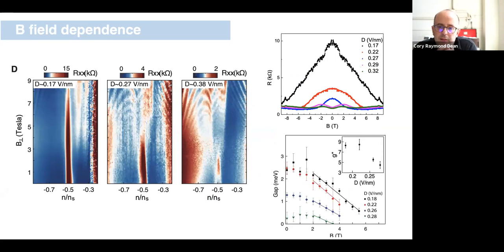Okay, so one of the questions immediately is, what's the magnetic order of this ground state at half filling? And the answer I'm going to give is that for this system, at least so far, we don't have a good understanding of that. I'm showing here some magnetic field dependent measurements of the half band insulator gap, so how that gap evolves as a function of B and as a function of displacement field. And what we see is that generally beyond some threshold magnetic field value, the gap indeed decreases. So the initial interpretation of that response would be that we have something like an antiferromagnetic insulator that describes this insulating state. But it's not so straightforward.